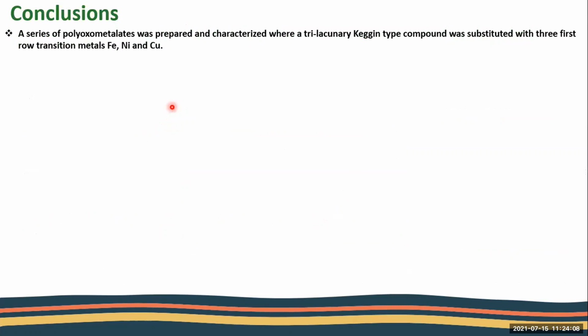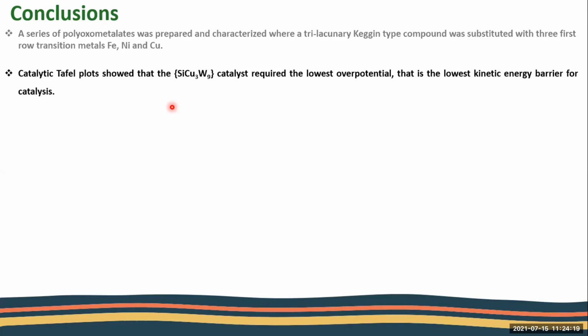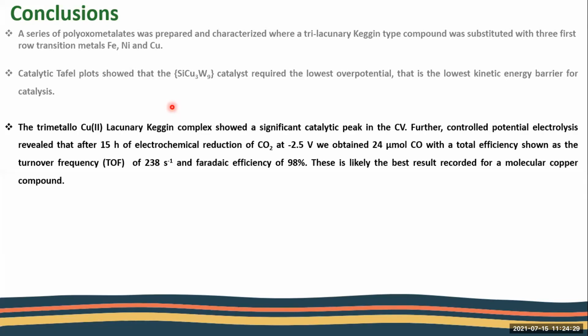So we can conclude and say that we prepared a series of catalysts of trilacunary structure that are substituted with first row transition metals of iron, nickel, and copper. Catalytic Tafel plots showed that the copper-3 catalyst required the lowest overpotential, that is the lowest kinetic energy barrier for catalysis. In the copper-3 complexes, we showed a significant catalytic peak in the CV, and in the electrolysis, after 15 hours at minus 2.5 volt, we obtained 24 micromole of CO with 238 turnover frequency and 98% faradaic efficiency. And this is likely the best result recorded for a molecular copper compound in the literature.